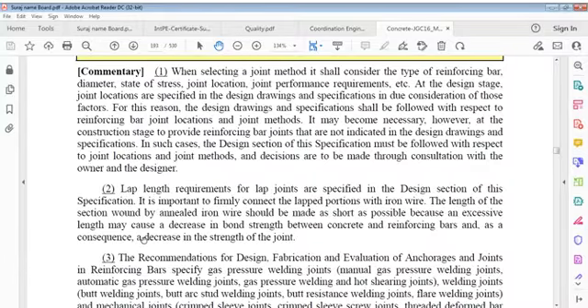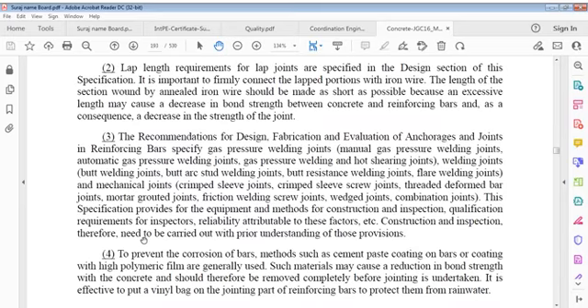Lap length requirements of lap joints are specified in the design section. It's important to firmly connect lap portions with iron wire. The length of the section wound by annealed iron wire should be made as short as possible, because an excessive length may cause a decrease in bond strength between concrete and reinforcing bars, and as a consequence, a decrease in strength of the joint.